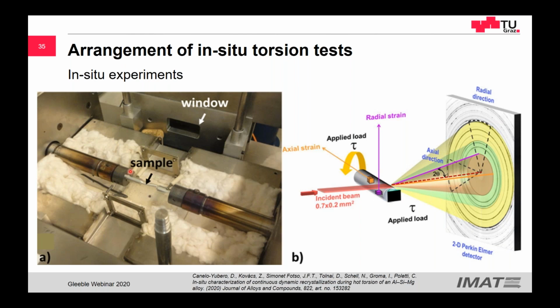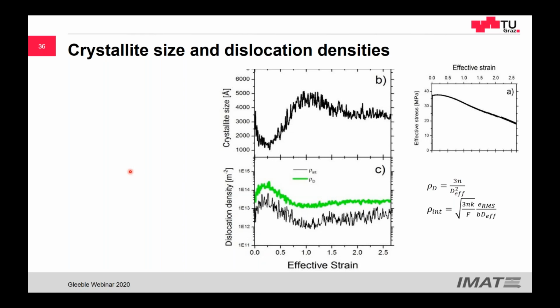And so we have done a lot of data treatment here. I just want to show one of the main results, maybe, which is the evolution of the crystallite size. The crystallite size is not the subgrain size, it's a bit smaller even than the subgrain. And you can see first this decreases and then it increases and then it reaches a steady state. The dislocation density increases and then reaches a steady state. And this is the effective strain, up to 3 more or less.